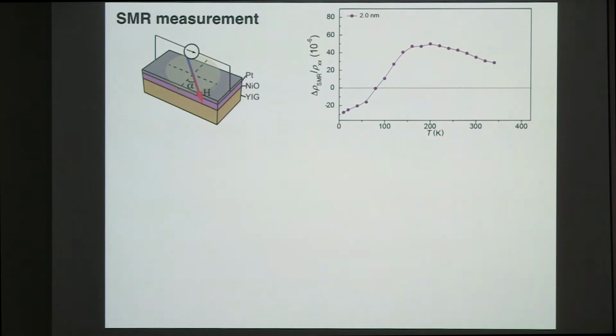Our way to approach the final solution is to do it pretty systematically. First, I show this 2 nanometer nickel oxide data here. You can see we have a sign change, which has been reported by other groups. And if we gradually increase the thickness of this nickel oxide, you still have this strange sign change behavior, but the sign change point increases to higher temperature. But still you have the sign change here.